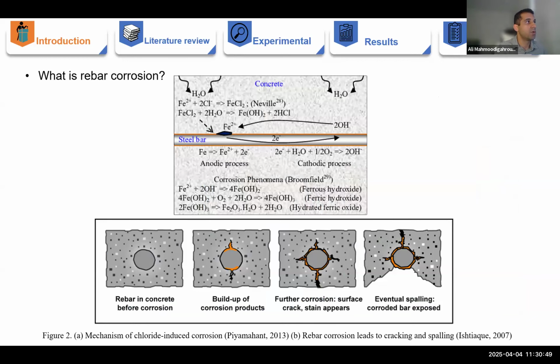But what is actually rebar corrosion? Basically, rebar is already passivated inside the concrete, which means there is a protective oxide layer on the surface that protects rebar from corrosion. However, corrosive species like chloride ions from the outside environment penetrate the concrete over time, reach the surface, and destroy the passive layer. And once the layer is compromised, rebar starts to corrode, making a lot of rust on the rebar, forming a lot of internal stresses, leading to cracking, spalling, and delamination.